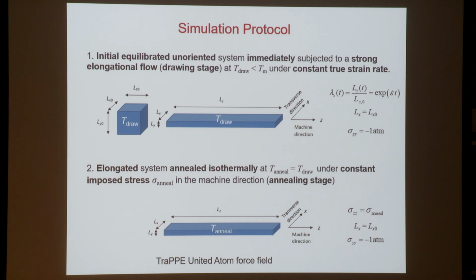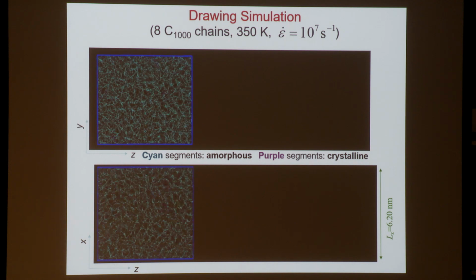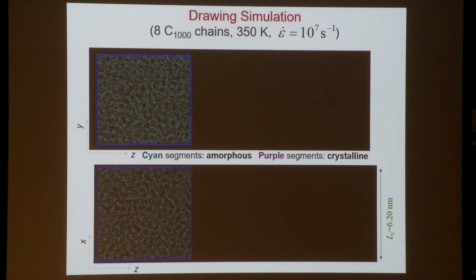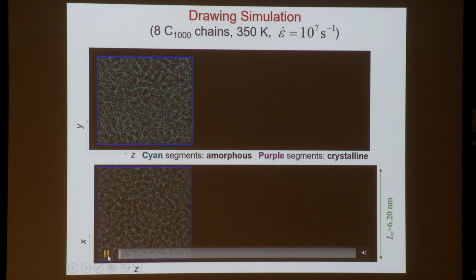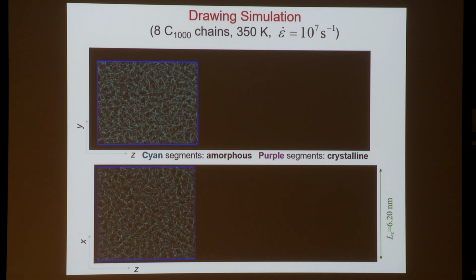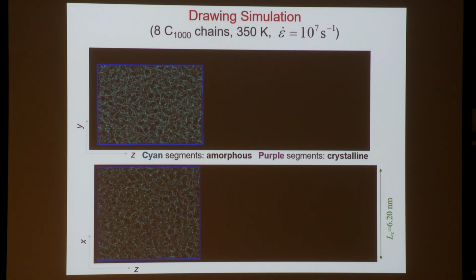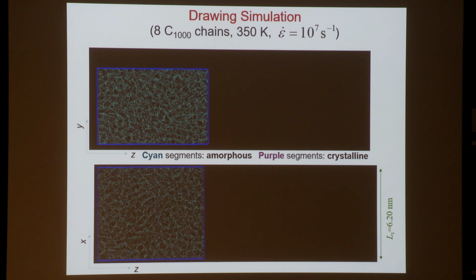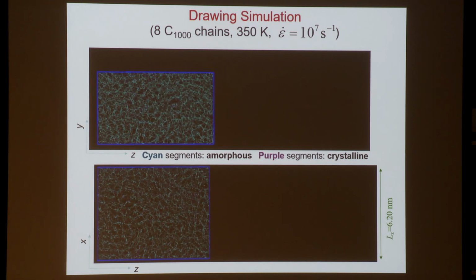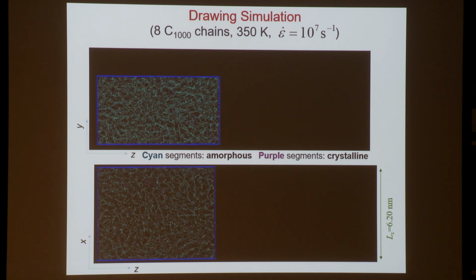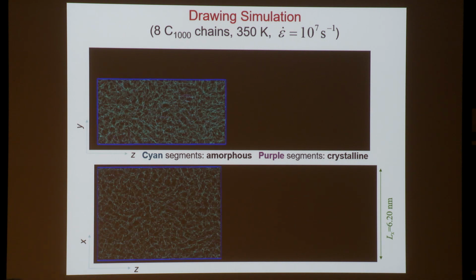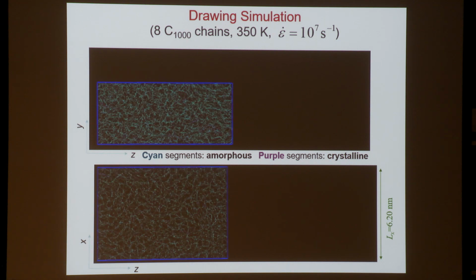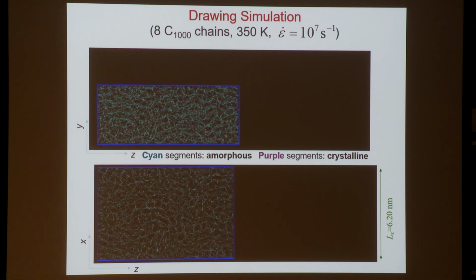So let's look at some movies of some very simple simulations on a very small system. This is 8 chains of C1000, a rather small system, at 350 Kelvin and at an epsilon dot of 10 to the 7th inverse seconds, quite high. And here we have tried to differentiate ordered regions, which will appear purple, from the amorphous regions, which are blue. If you look closely, you will see that some purple regions emerge and then they dissolve again. This is fluctuations leading ultimately to a nucleation phenomenon.